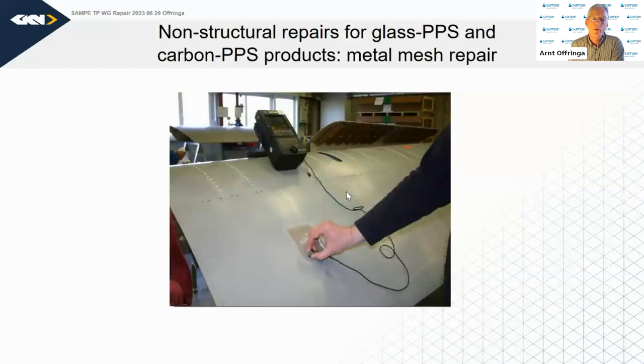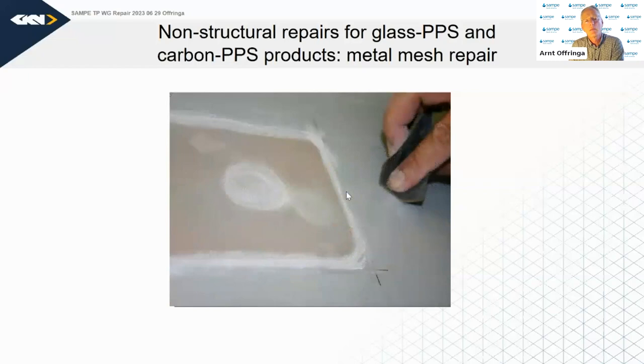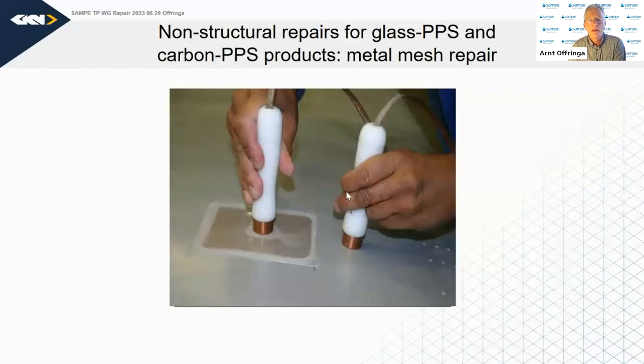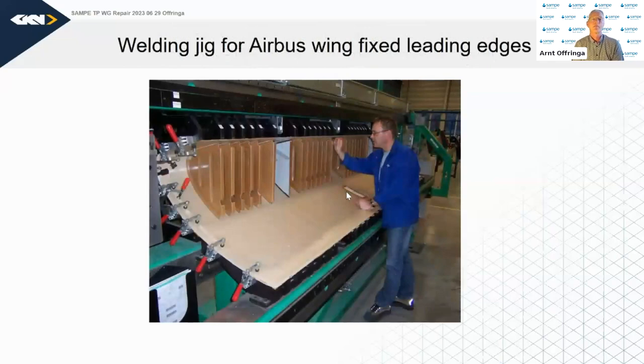If it's a metal mesh repair, it's important that there is electrical conductivity. So there are measurements to be done. For example, this is the NDT inspection, but also we have to measure the electrical conductivity. With some light sanding you lay bare the aluminum mesh on the repair patch and on the product itself. Then with two electrodes you measure and see that we have electrical contact between these two. So these are cosmetic repairs done with epoxy resin, which can be done in the field anywhere in the world, no particular equipment necessary.